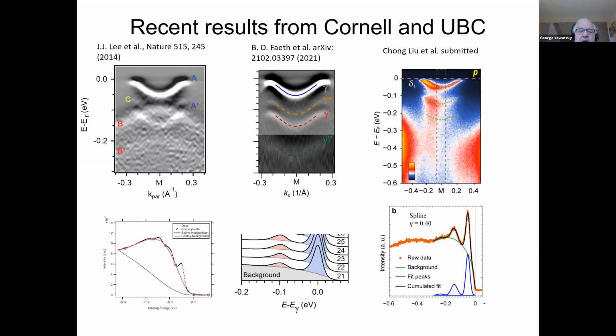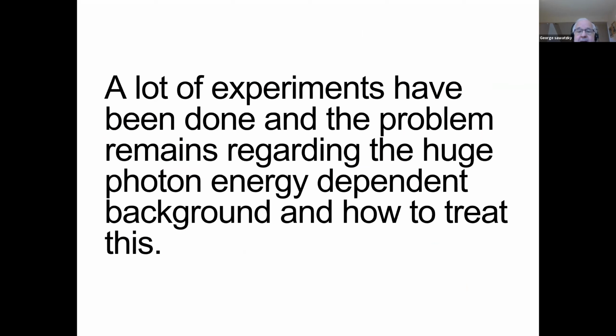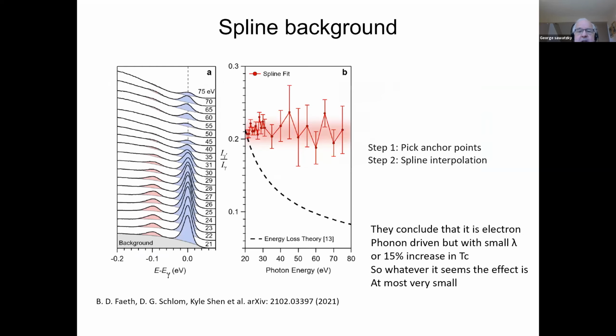And many people have tried to measure this. It's very hard to do simply because of the very large background. If you look at this spectrum here on the right at the bottom, you have this very huge background, and you don't know what the shape of it is inside here. So it's very difficult to say what the relative intensities of these peaks are. But there's a very recent experiment, and as I say, there are a lot of experiments. I know ZX's group at Stanford and in Berkeley have tried very hard also. We have also, but we simply couldn't make much sense of it.